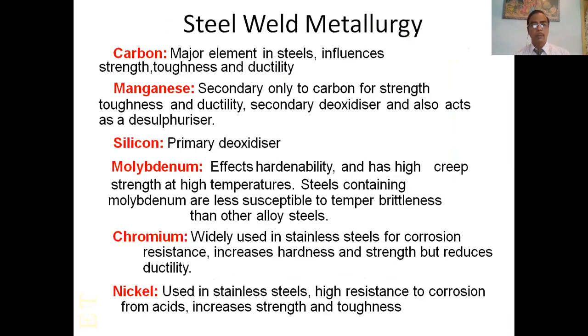Steel weld metallurgy. Carbon, the major element in steel, influences strength, toughness, and ductility. Manganese, secondary only to carbon for strength, toughness, and ductility, is a secondary deoxidizer and also acts as a desulfurizer. Silicon is a primary deoxidizer. Molybdenum affects hardenability and has high creep strength at high temperatures. Steels containing molybdenum are less susceptible to temper brittleness than other alloy steels. Chromium, widely used in stainless steel for corrosion resistance, increases hardness and strength but reduces ductility. Nickel, used in stainless steel, gives high resistance to corrosion from acid and increases strength and toughness.